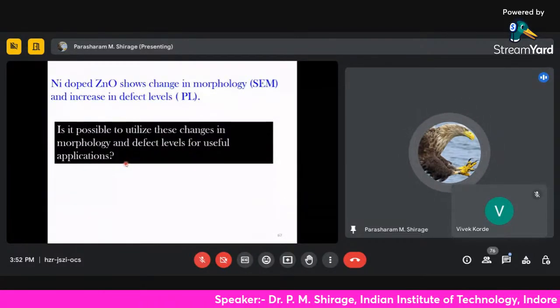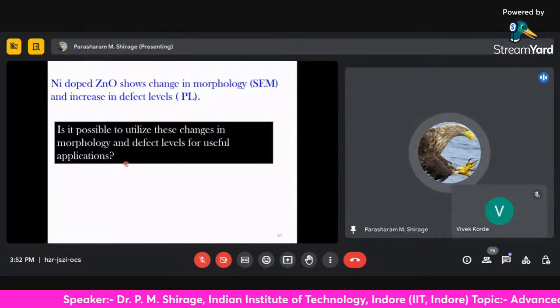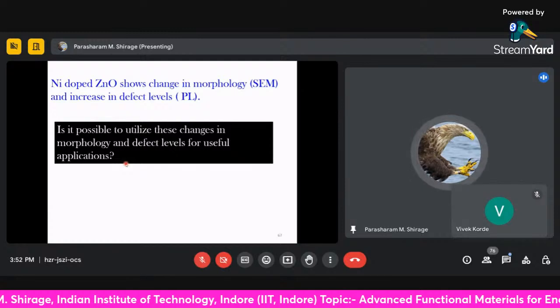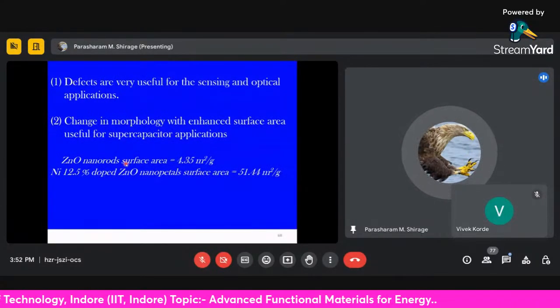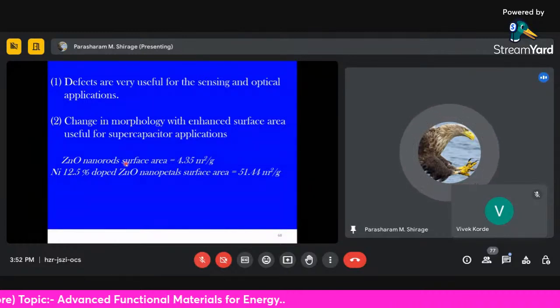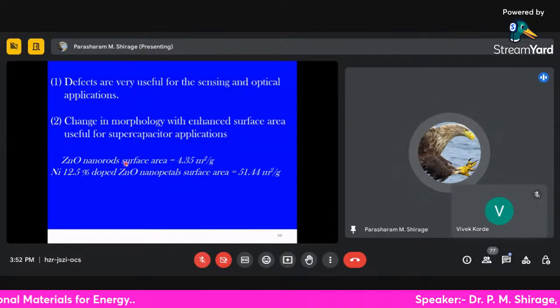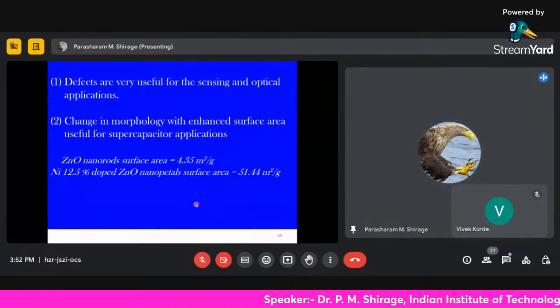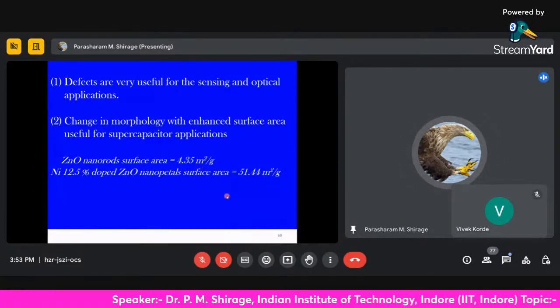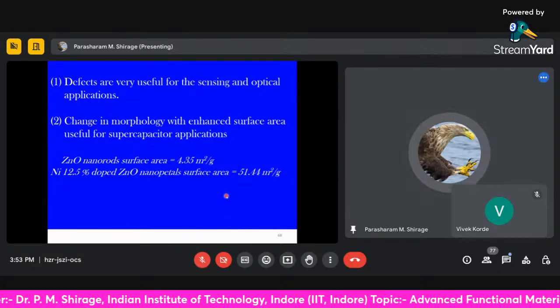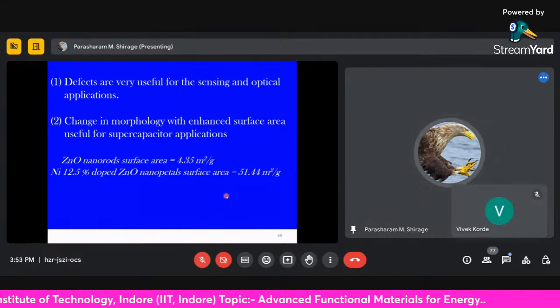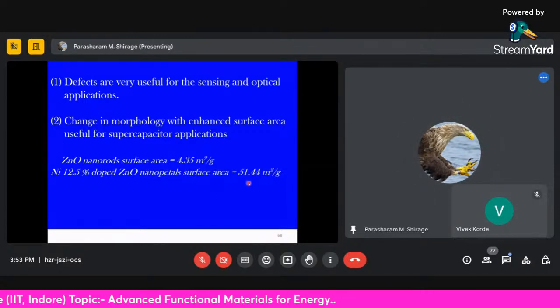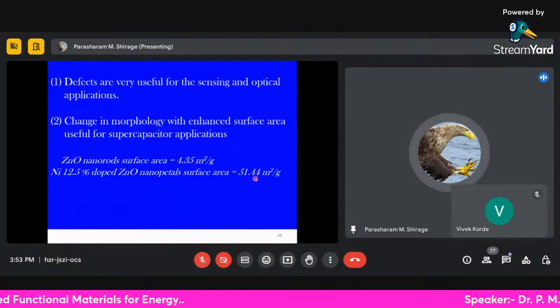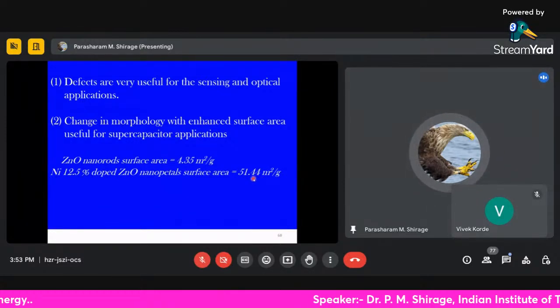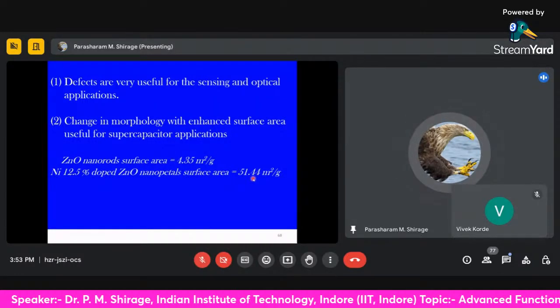So we got two different things now. The change in the morphology is going on, the change in the defect level is going on, and we can utilize this for different applications. Defects are very useful for sensing applications and optical applications. Then change in the morphology with enhanced surface area is useful for supercapacitor applications. For example, zinc oxide rods have a surface area of 4.35 meters square per gram. And when we dope with 12.5%, it increases from 4.35 to 51.44. Ten times higher surface area we are getting. And I already mentioned that rod-like structure is changing to flower-like structure in case of nickel.